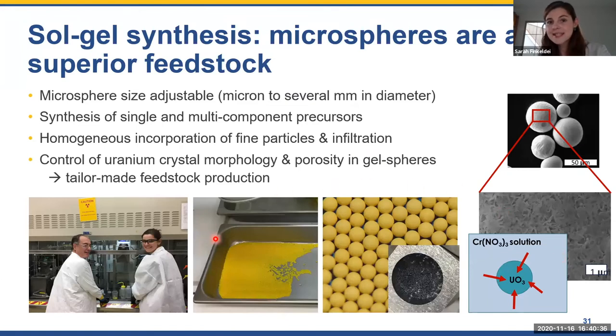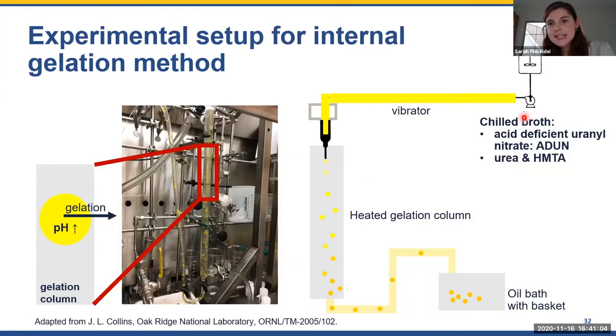In sol-gel synthesis, what you do is you fabricate microspheres. And it can be done for a lot of different chemical compositions. The beauty of this technique is that we can adjust the microsphere size from the micron to the millimeter level, and we can homogeneously incorporate fine particles and filler materials, and we can also control a bunch of parameters like morphology and porosity of those spheres. So here's a schematic drawing.